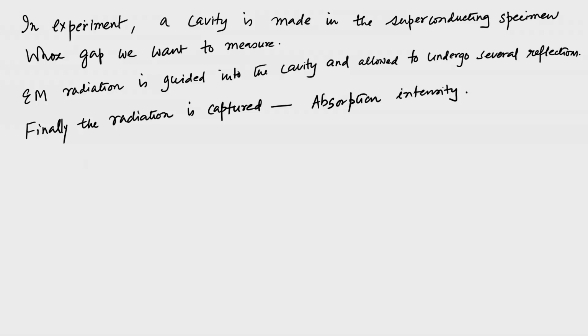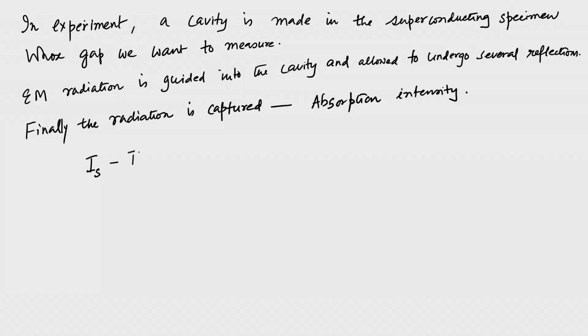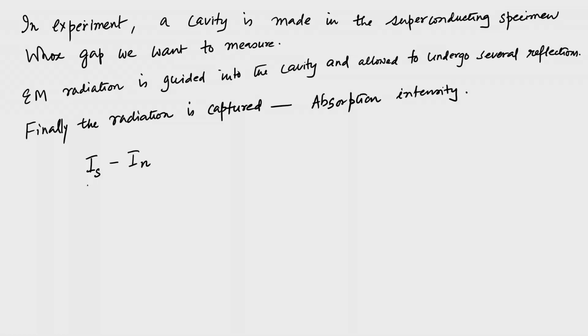But before that, what is plotted is actually IS, assuming that the specimen is in the superconducting regime, and minus IN. So, this means that the superconductivity is destroyed while the experiment is carried on, keeping at the same temperature, but using a magnetic field. We know that a magnetic field destroys superconductivity, giving rise to a normal state. So, that normal state intensity is also captured and divided, that is the normalization, giving the normalized intensity.